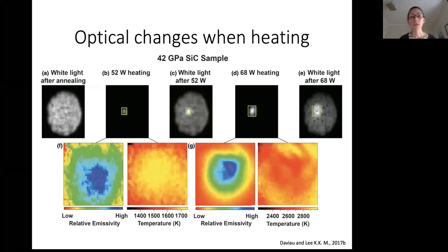So we investigated these optical changes when heating to see whether they correspond with this potential phase change or melting behavior that we're observing. In this kind of busy figure, we're looking again at a silicon carbide sample that was just loaded with a pressure medium. This first image, white light after annealing, on the left, shows that the entire sample became more transparent after heating. This is transmitted light. Immediately next to that image is the light emitted from the sample while heating in this location. And then white light after that heating shows that that region of the sample became more transparent. It's a little bit brighter there. When we then heated at a higher wattage, this one's 68 watts, we saw it become more transparent as well as achieve that little opaque region in the center.